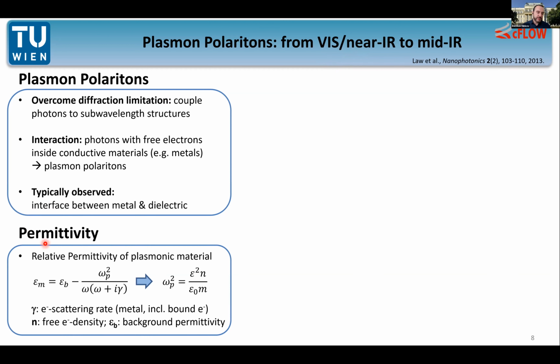But let's have a short excursion here, also a bit into the theory of that. So the important characteristic here is the permittivity. So how does the material on which we shine our light react to this external field, basically the optical field that is applied to the surface? And we can calculate the relative permittivity of this material, for example, of our metal. And we see that we have a strong dependence on the plasma frequency of the metal or of the material. And the plasma frequency is basically the resonance frequency of the electrons in our metal. If we go one step further, we can calculate and express the plasma frequency and see that it's mainly dependent on the electron density that we have.